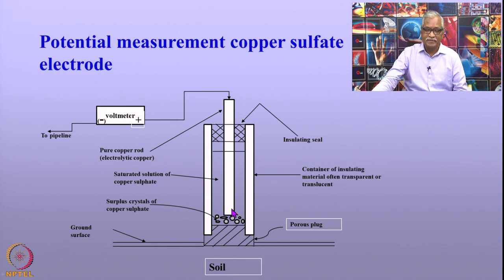In fact, this is an advantage, because in the field by looking at this, you will notice that the concentration of the copper sulfate has remained unchanged. The advantage of using a saturated copper sulfate is that the concentration of the copper sulfate in the solution, which means the copper ions in the solution, remains unchanged, and so this electrode has a potential which is not changing. For some reason, if the concentration of the copper sulfate solution changes, then the potential of this electrode changes. So, saturated copper sulfate solution is a versatile way of ensuring that the potential of the reference electrode remains undisturbed.